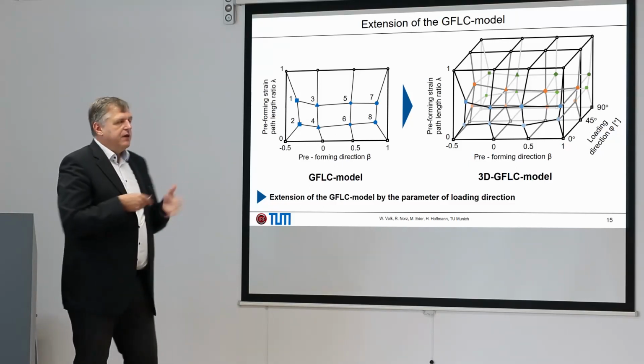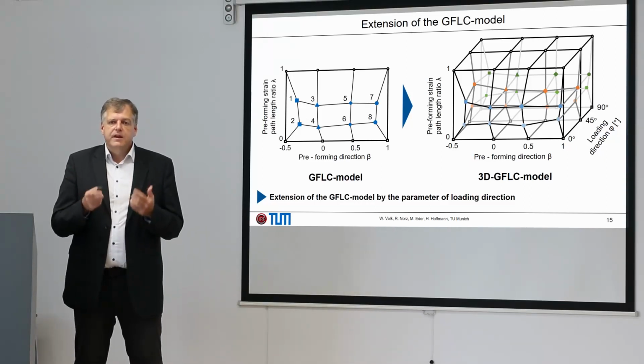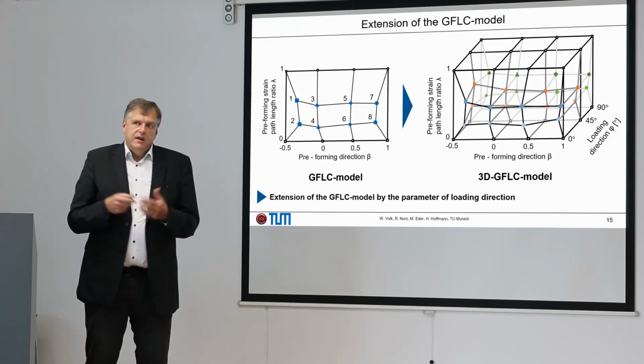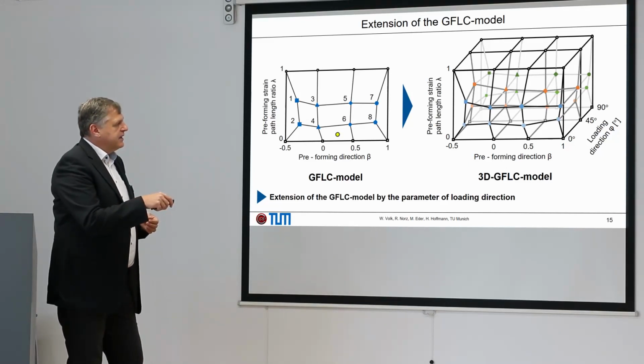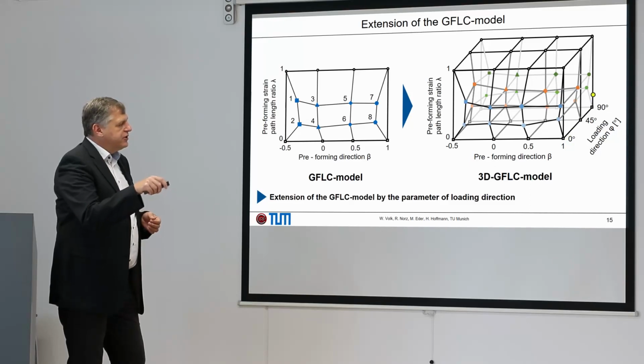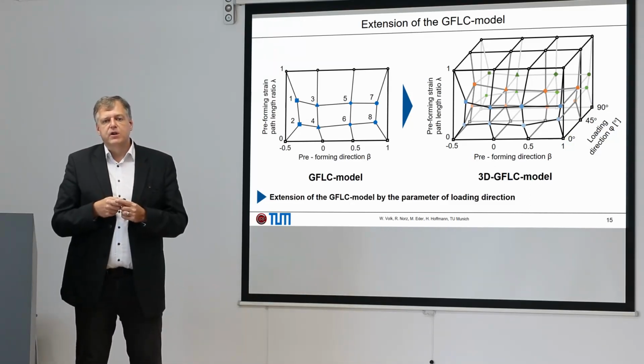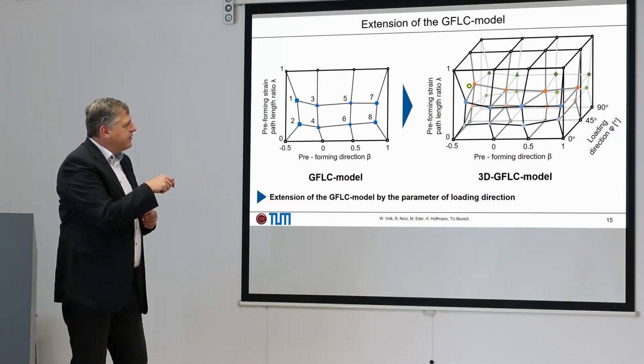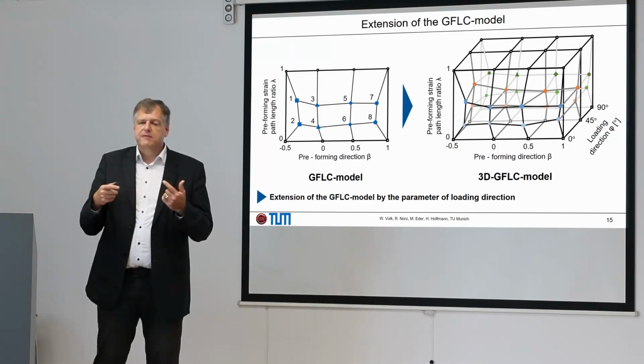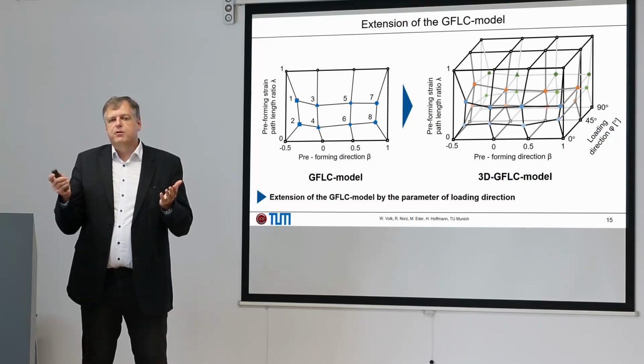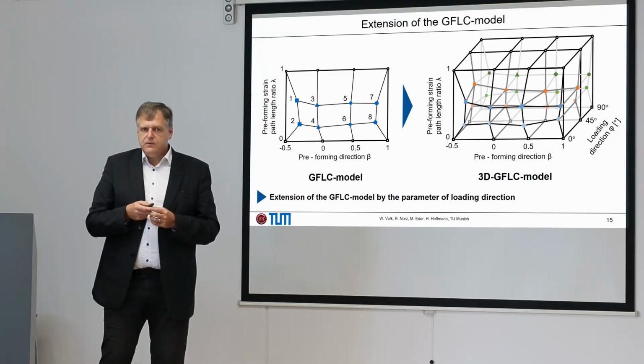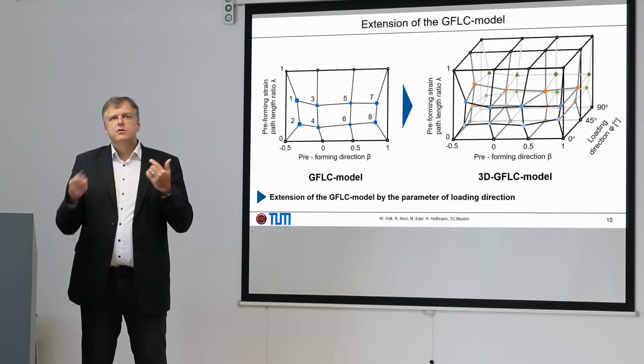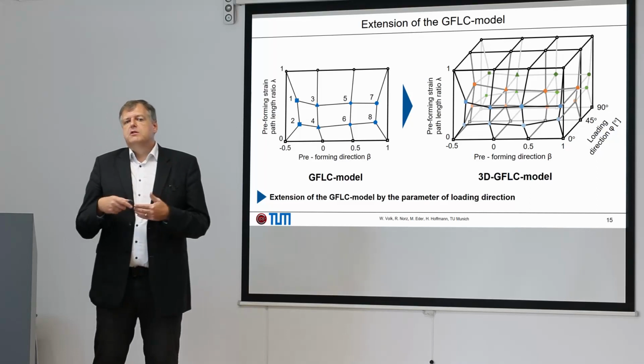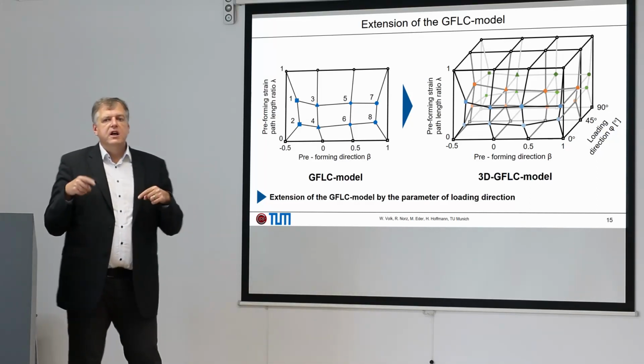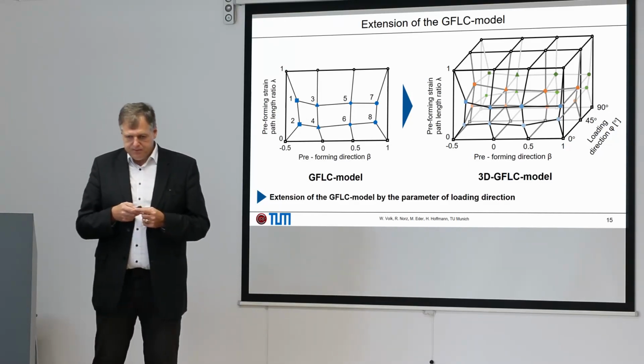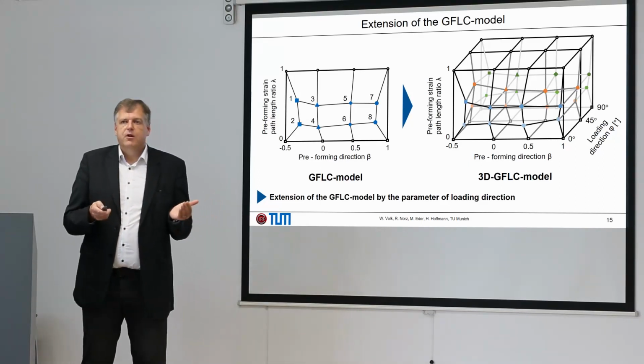But it's still isotropic. And now what we have to do is to add this anisotropic information within the framework of this phenomenological description. Inside the phenomenological model, it's quite easy because you can add a second direction where we have the loading direction or the change with respect to loading, respectively, rolling direction. So that means we have to do experiments on all these points, and then it's possible to interpolate the remaining FLCs, which is measured on every point, just with the same approach functions as we have done this in the GFLC. So you have to do the experiments. You can use these experiments within your phenomenological model, and now it's possible to predict arbitrary combinations of non-proportional and anisotropic material behavior. Therefore, the next step, of course, is how to validate this.